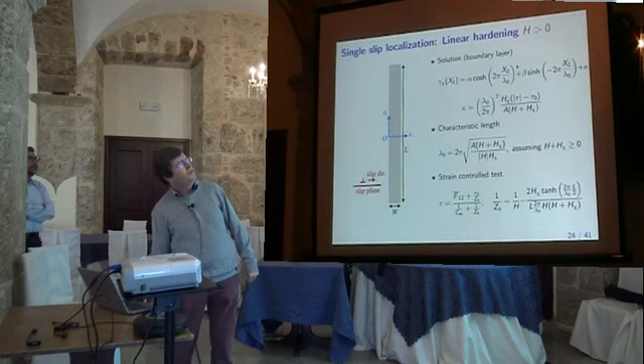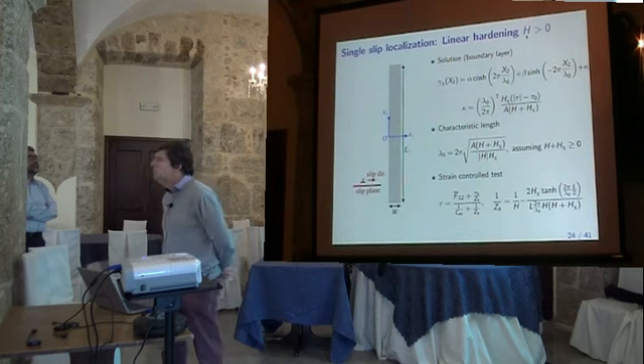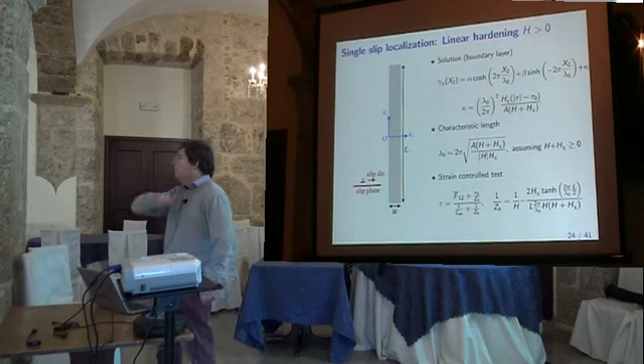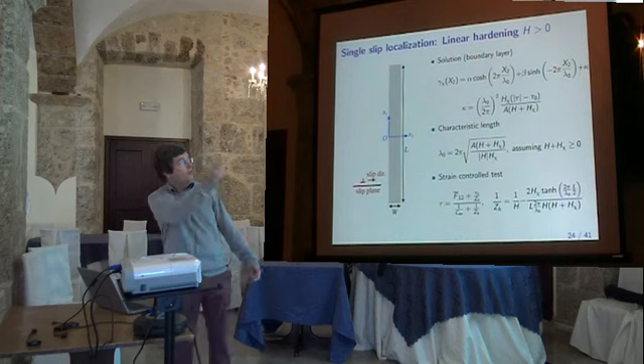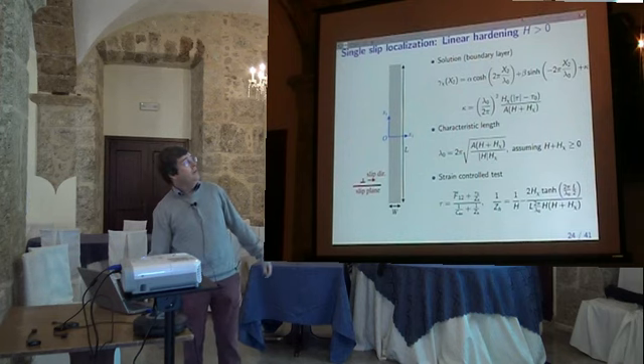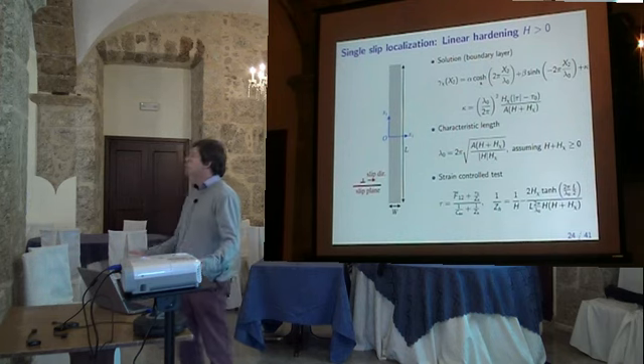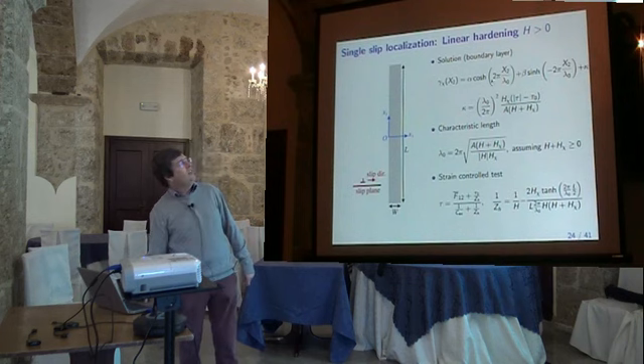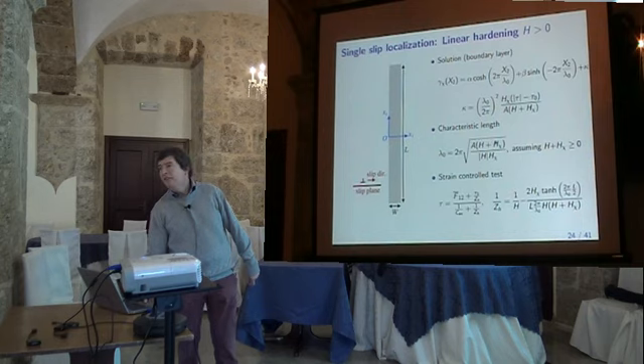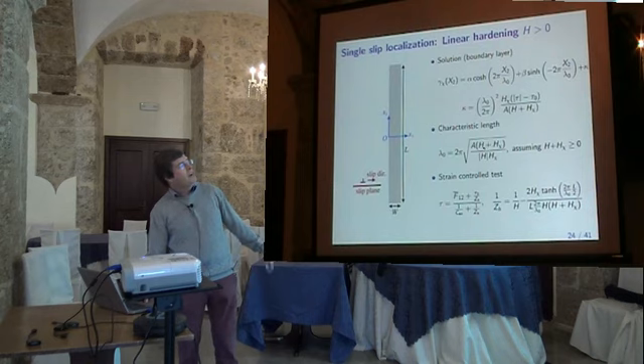First case, H is positive. So hardening, and we solve the equation. This is an easy equation, there is nothing special. And you find an exponential solution with a characteristic length, lambda 0. This characteristic length is related to the hardening modulus and the penalty constant. And you see, if you let the penalty go to infinity, you will have a special case where you have this,